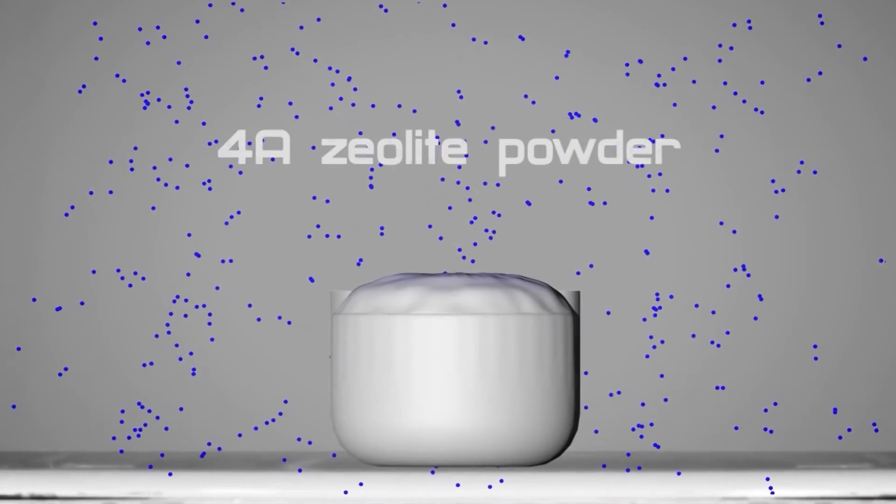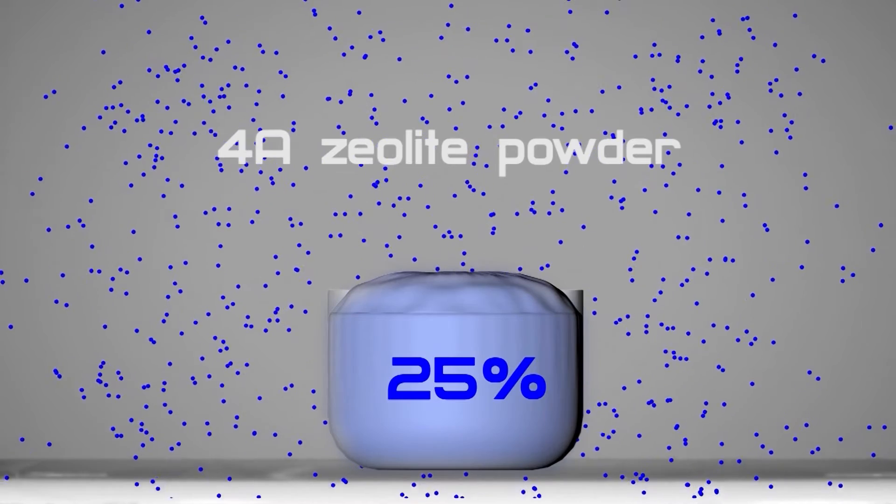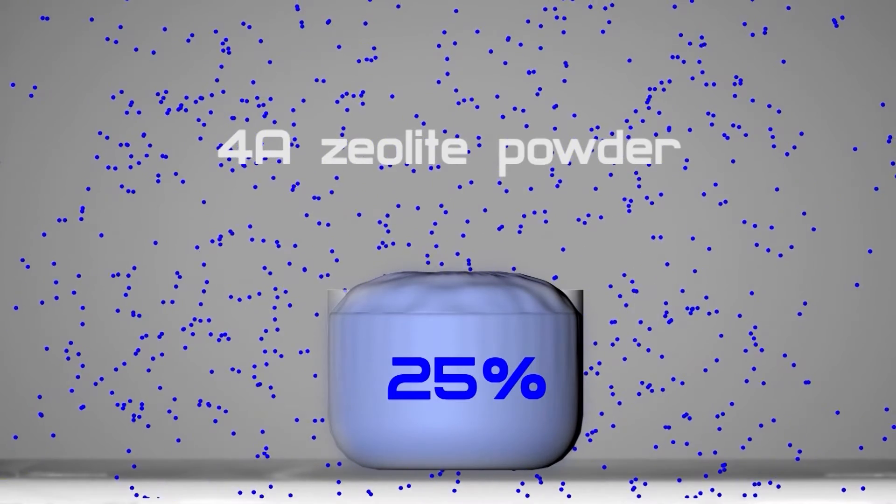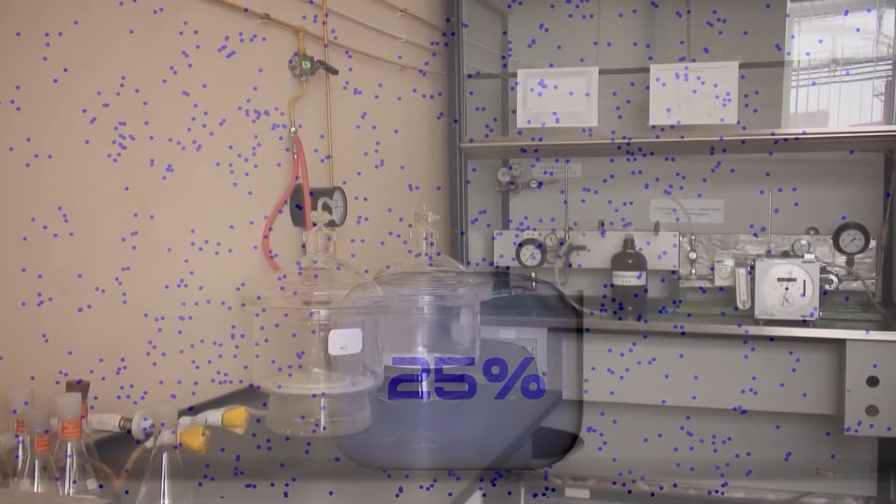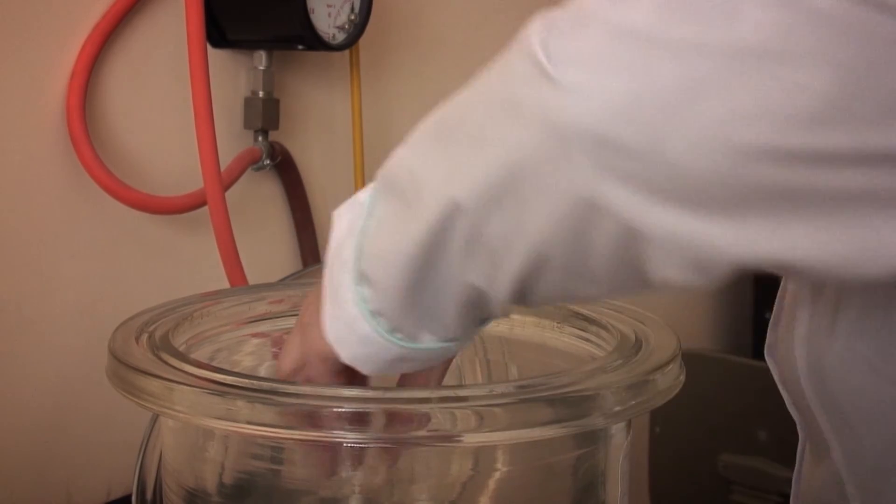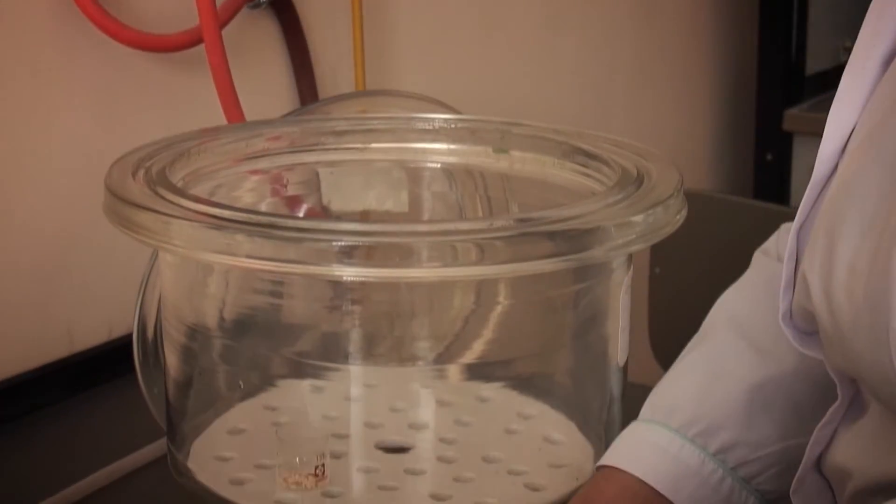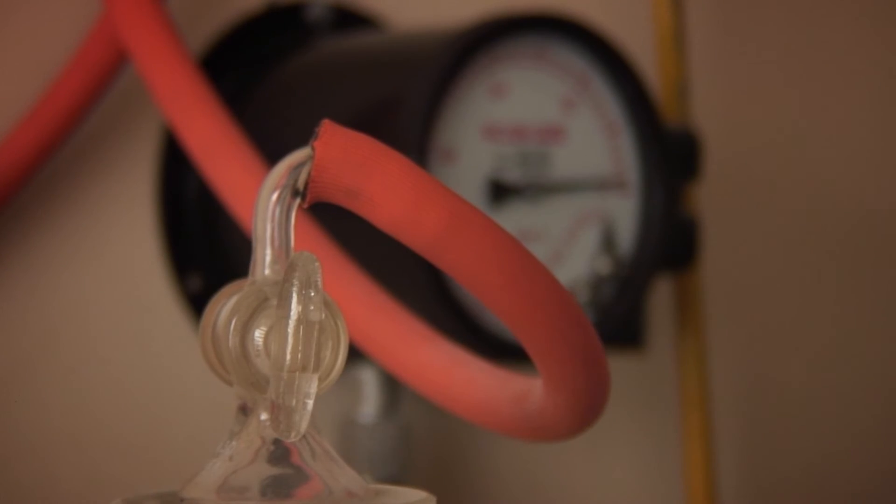Theoretically, this powder should have a static water capacity of 25% at 100% crystallinity, which means that under certain conditions, the zeolite can absorb 25% of its weight in water. KNT group specialists measure water absorption capacity at 25 degrees centigrade and a humidity of 10%. But zeolite powders alone are insufficient for use in gas drying.